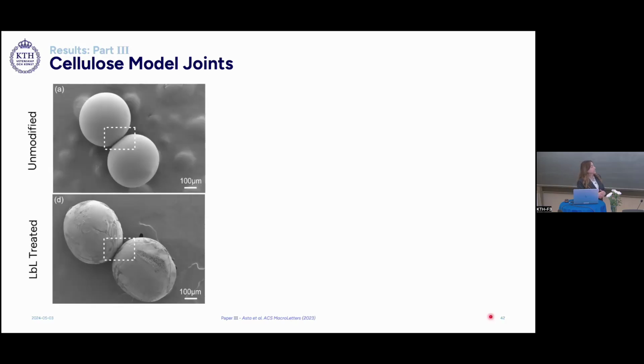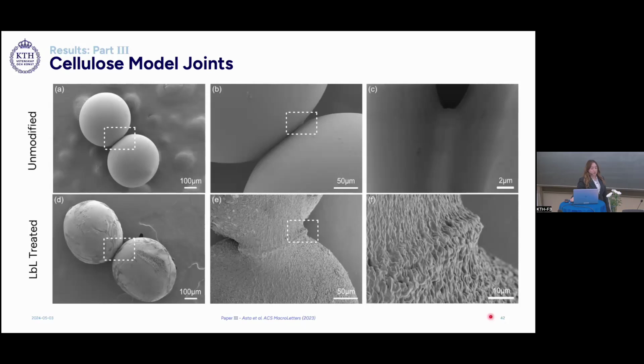This is done using SEM, where we can see that the AFM images are further supported, where we see the increased roughness of the LBL treated materials compared to the unmodified ones. And when we look in more detail, we can see that the surfaces are very affected by the LBLs, and the joining is also very different in the LBL treated materials.